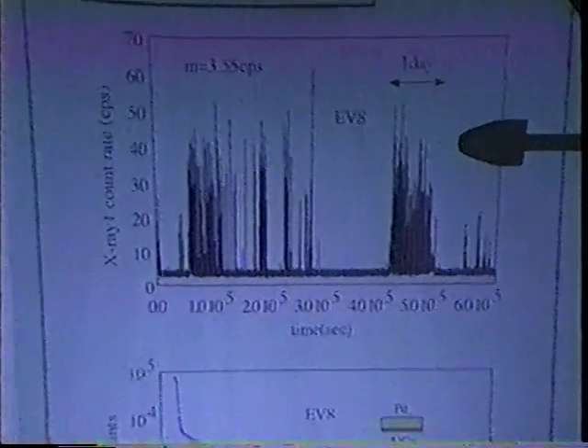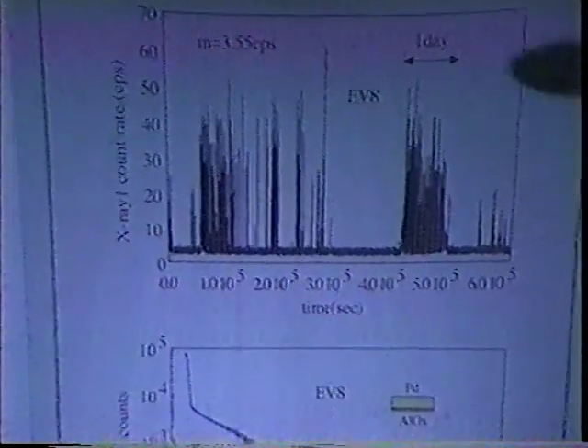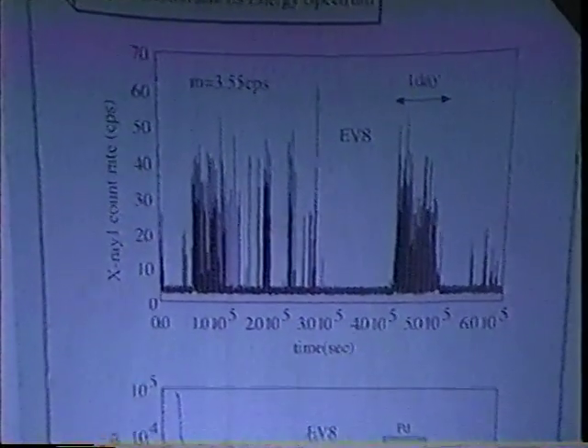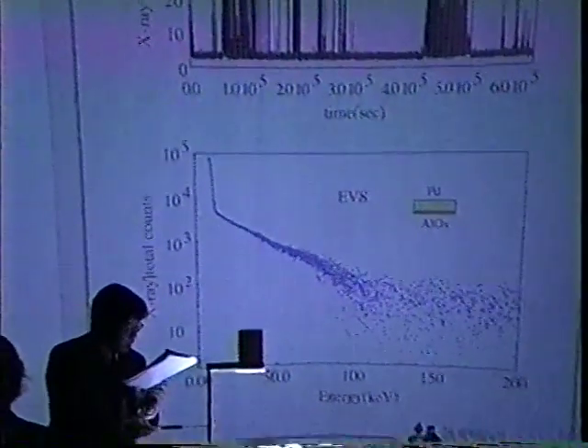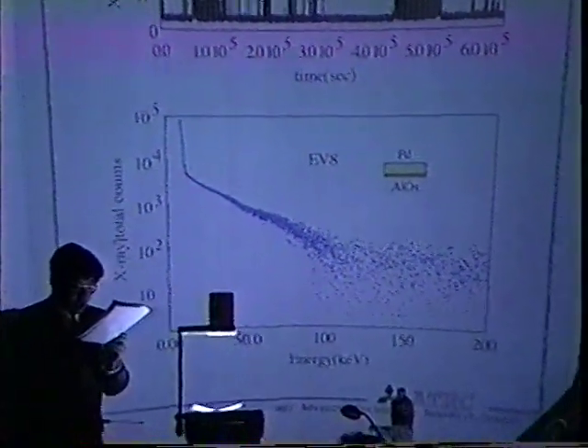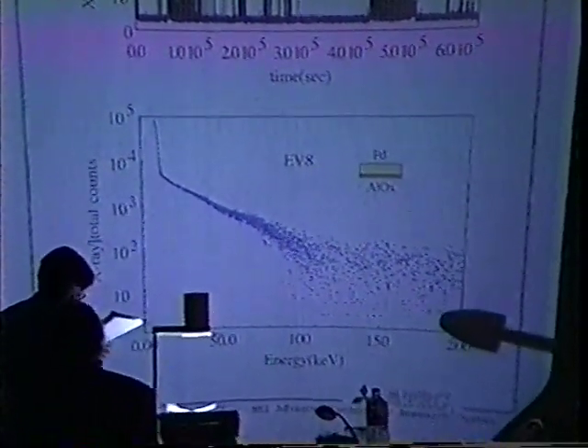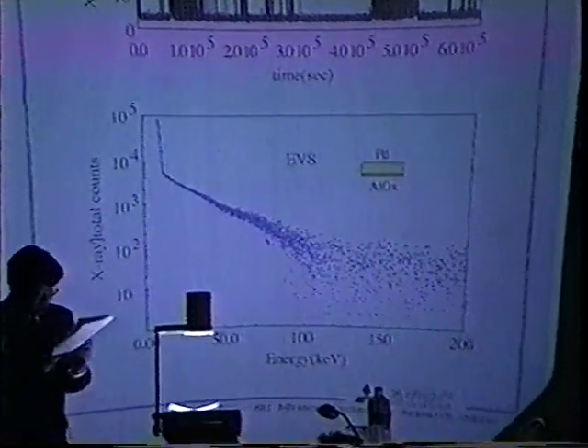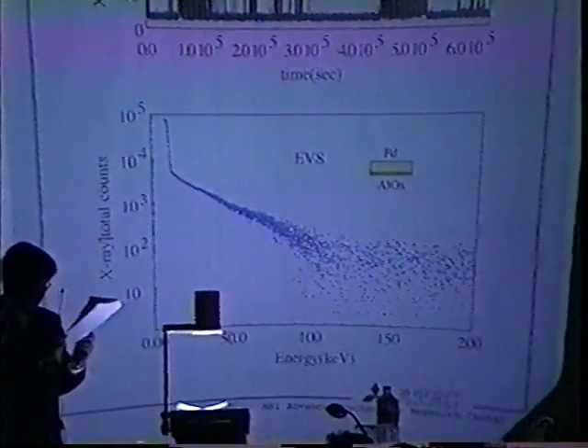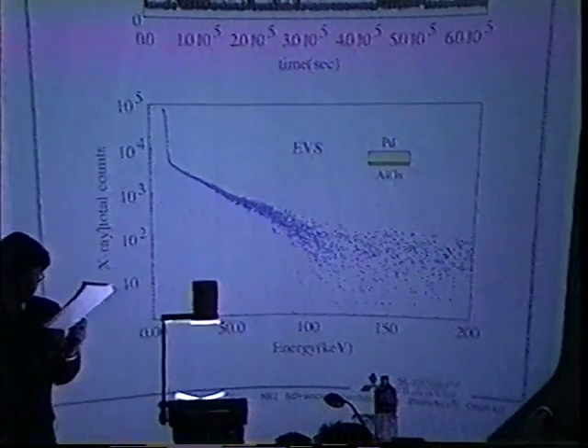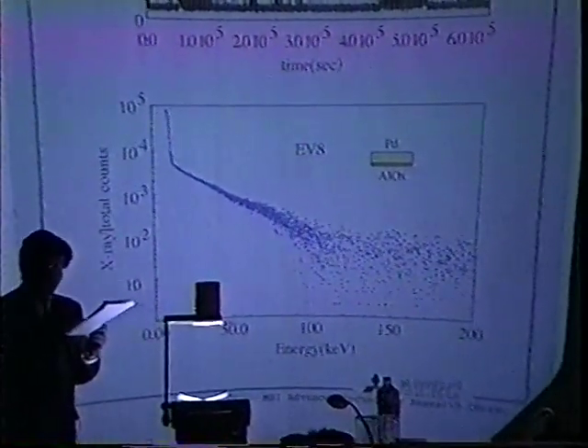And around this period, X-ray emission lasts for about 1 day. Energy spectrum of the X-ray emission is shown in the lower figure. X-ray energy distributes continuously like this. However, at present, we cannot explain consistently why such an energy spectrum was obtained.